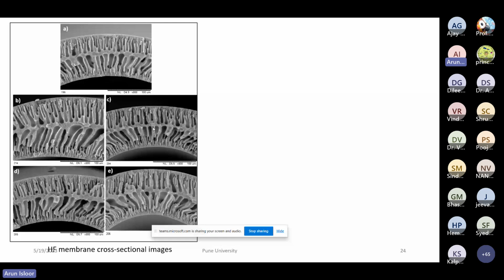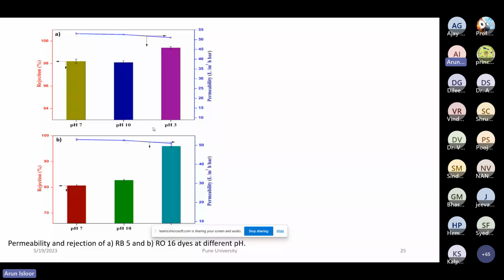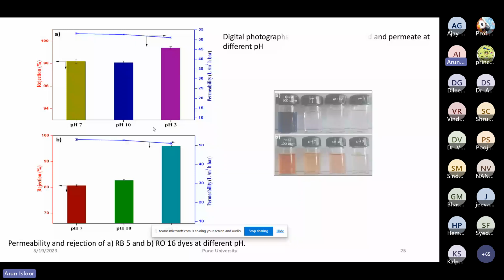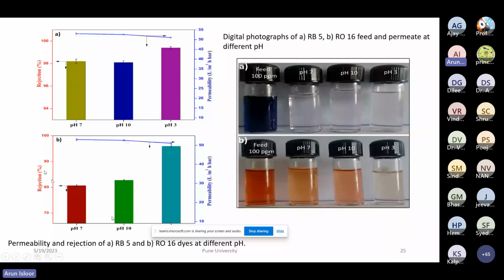And these membranes were used for testing the permeability of the two dyes, namely RB5 and RO16. In RB5, it showed almost 99% removal, and in RO16 it showed about 93-94 percent removal. It is mainly because of the size exclusion.